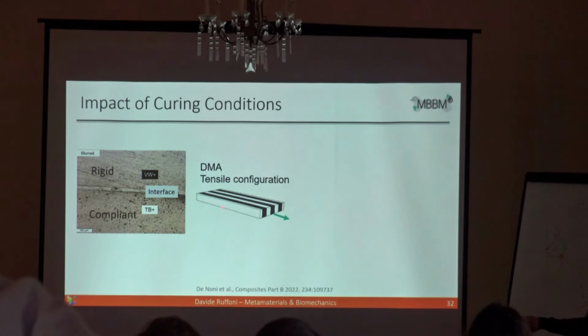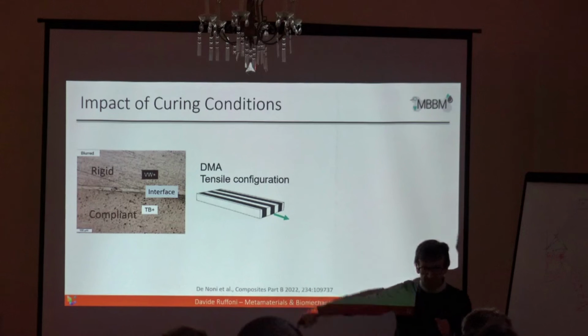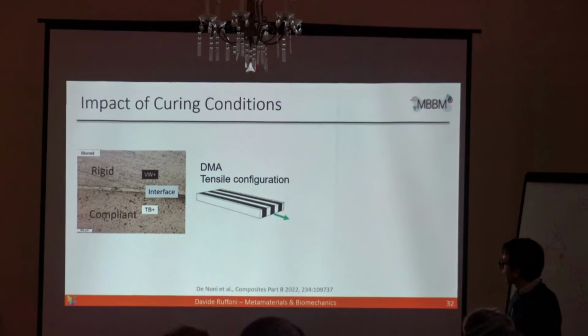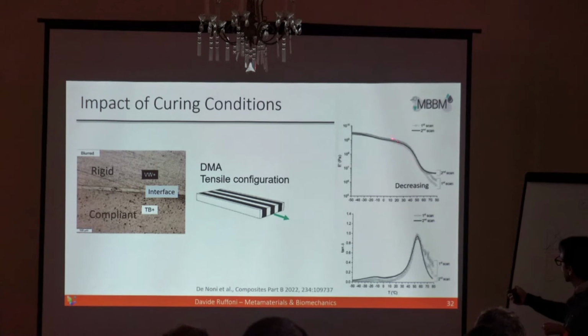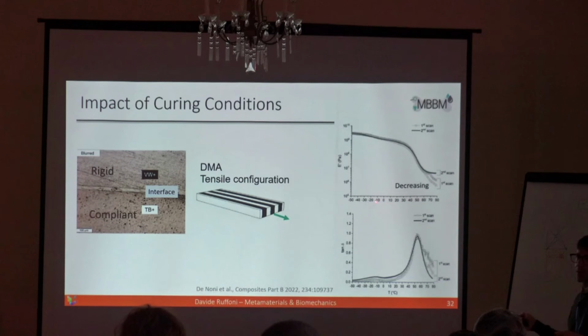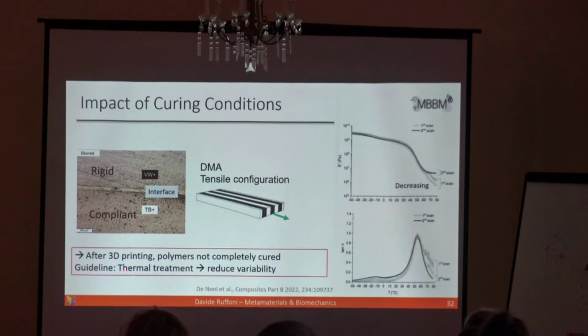So in a very simple tensile configuration, when we are building materials, white is stiff and black is soft. We do now DMA in tension, and the first thing that we observed is that we scan the same sample several times at small displacement, and the first scans are not highly reproducible. This is something that we observe both in the storage modulus and in the transition temperature. And after the second scan of the same sample, the reproducibility increases. So this is a message that after the 3D printing, even though the company says that the polymer has been cured completely, it's not actually the case.